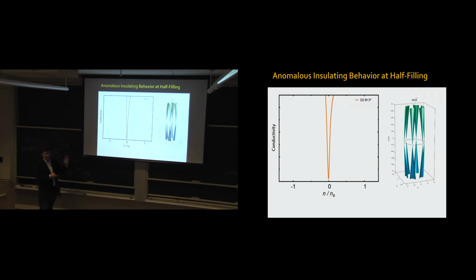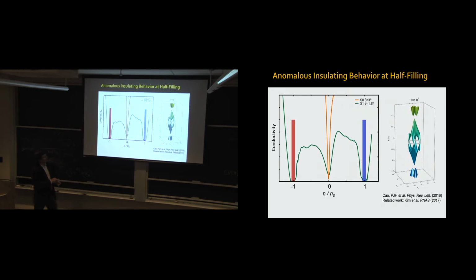Let me now show you data from a device with a smaller angle, but not yet magic, 1.8 degrees. Within the energy window accessible to our density, we have near charge neutrality, and this still looks like those graphene Dirac cones, so you have a V-shape near charge neutrality. But as I add 4 electrons to my system, I hit this band gap, so the system becomes an insulator before I can start adding charge to the upper band and conduct again. So I go through this insulator behavior when I put 4 electrons per unit cell before I conduct again.